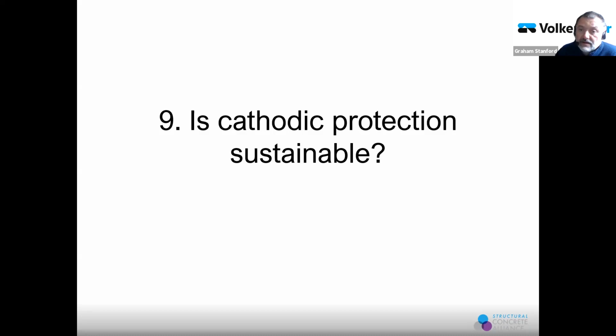I think we can. The basic premise of a lot of cathodic protection is that we don't remove chloride-infected material. We remove the loose material, and we look at how we can treat the infection with cathodic protection, and keep that sound material, albeit encased with chlorides, in place, and protect the steel by putting in the cathodic protection system. So yes, the very quick answer is cathodic protection can be sustainable, but you'd have to look at it from a specific point of view.